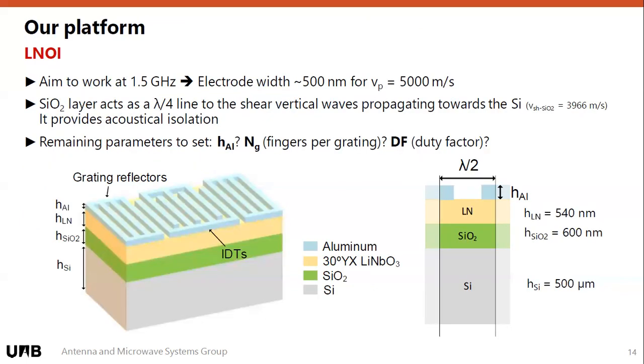Without diving into the discussions that led to choosing these values, in this case we're going to be using 40 fingers per grating because we did an initial experiment using 20. We saw that there was not enough reflectivity, so with 40 we're okay. And with the duty factor, we did the same experiment, and we know that for a 40% ratio between metallized and non-metallized region, we are at the position in which we have the better coupling. And we avoid exciting other modes because there are other dependencies with the duty factor that we don't have here in this presentation.